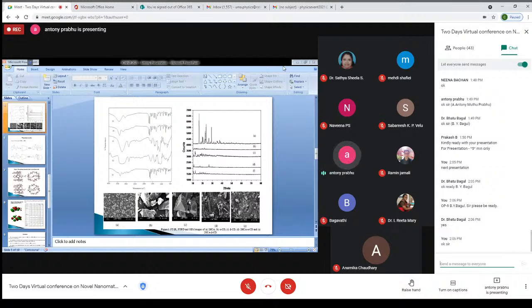Then another one, powder XRD. Some of the powder XRD patterns appeared to be of crystalline nature, but the other two complexes' powder XRD patterns are of amorphous nature. Another one, SEM image. The individual compounds' and complexes' SEM images are different in many places, which can be seen in the SEM images.